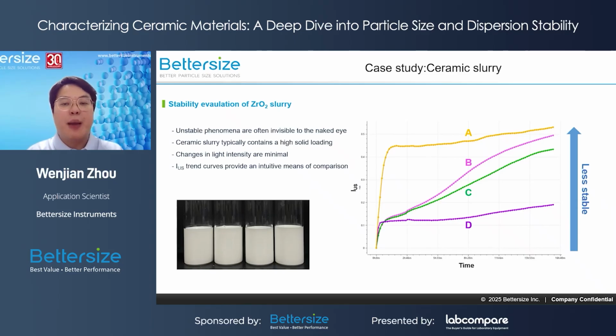However, when we compare their IUS trend curves, we notice that sample A shows a sharp increase in IUS at the very beginning, and then the increase slows down, and sample A is the most unstable during the measurement. But the IUS values of samples B and C grow rapidly later on, and probably exceed sample A if we extend the measurement time.